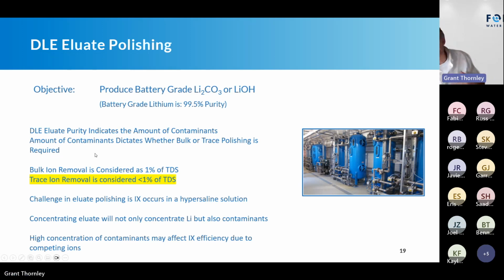So, DLE eluate purity. We talked about selectivity, which we know is that this is going to select the lithium and pull it out of the brine, but really what we're focusing on here is what the eluate purity is, meaning the concentration of contaminants coming over in that eluate. And remember, because we've concentrated, we've removed water from the eluate. That means not only did we concentrate the lithium, we've also concentrated the contaminants.